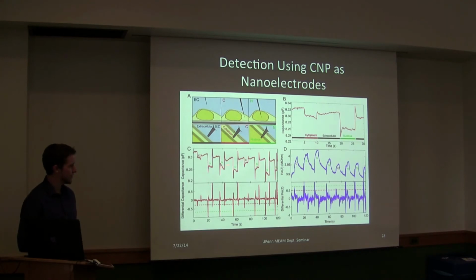We can look at both the capacitance and real part of the impedance. And then if you're looking to automate this process, we can look at things like the time derivative of the data, where in the time derivative, you'll get these spikes corresponding to large changes. And so you could potentially set a threshold value that is related to the downward motion of the pipette to detect penetration.